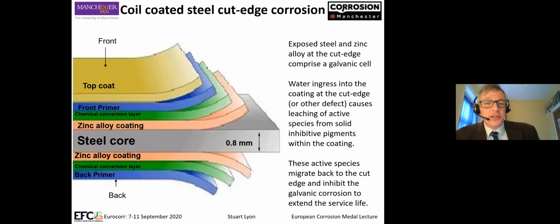We then moved on to coil-coated steel. The big thing about coil-coated steel is the cut edge. It's a very well-engineered system. Steel core, we have a zinc or zinc alloy coating, a chemical conversion layer, primers containing the inhibitor, and on the top face, a visually attractive material with UV protection and an appearance. So exposed steel and zinc alloy at the cut edge comprise our galvanic cell. And essentially, this is the big driver for corrosion of these systems.